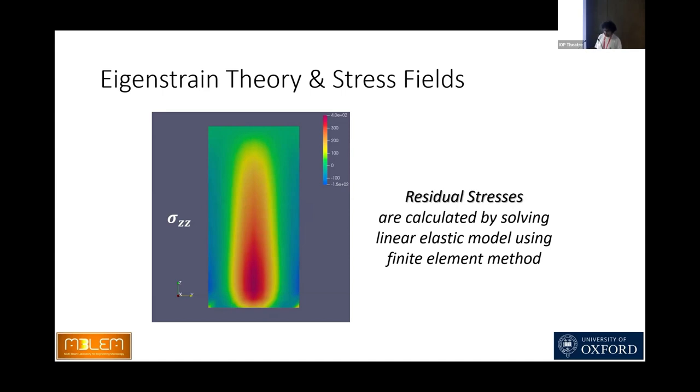Residual stresses are calculated by solving the linear elastic model using finite element method, using the eigenstrain field previously created. We call them residual stresses because there is no external load, and the source of these residual stresses are only eigenstrains.